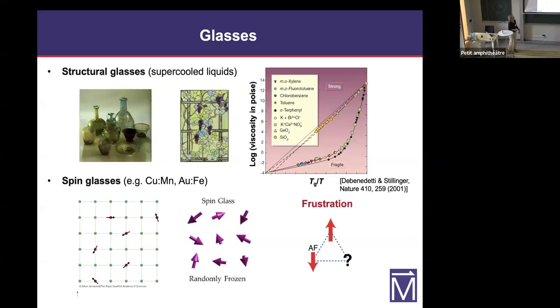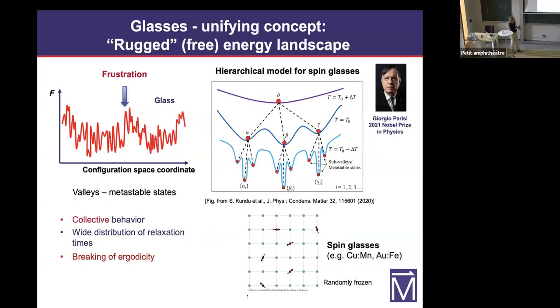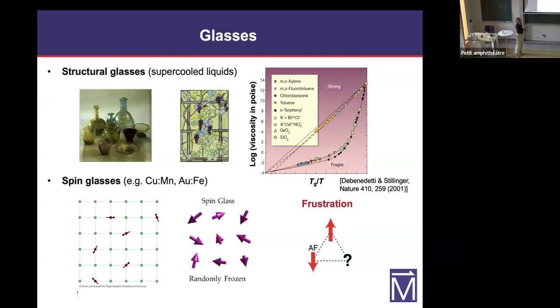All right. So, as I already said, the best known example of systems that are trapped in states far from equilibrium are glasses, and everybody is familiar with structural glasses, such as window glass. These are basically liquids which are cooled very rapidly, such that they are not able to reach the lowest energy state, which is that of a crystal, but instead the atoms get stuck in some random configurations. And as you cool such a liquid down, you can see that the viscosity shoots up by 16 orders of magnitude. So they become extremely viscous. This is why you cannot see them flow.